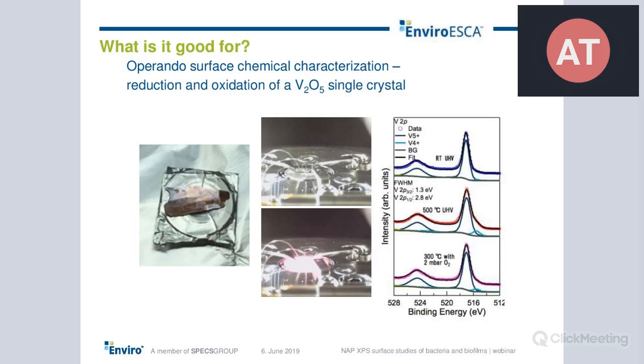And finally, we let oxygen in, 2 millibar of oxygen, and we kept the sample at 300 degrees C. And what you then see is that you reoxidize the vanadium, you lose a lot of the 4+ state vanadium, and you restore the 5+ vanadium here. So this is also a pretty nice experiment demonstrating how you could work in catalytic or surface reactions.